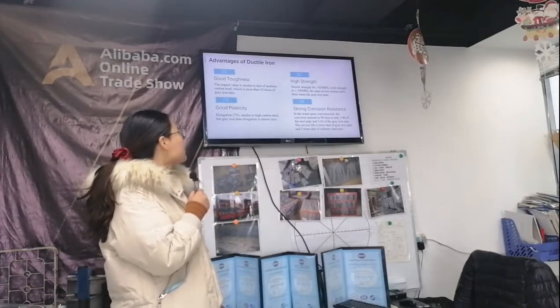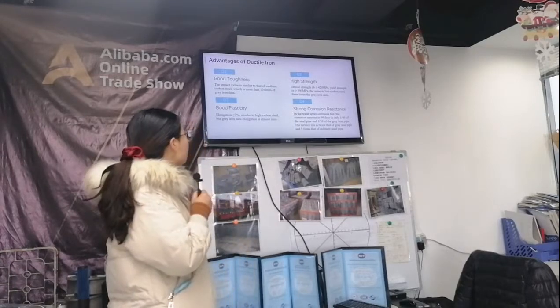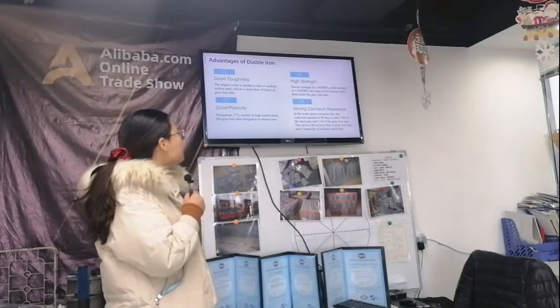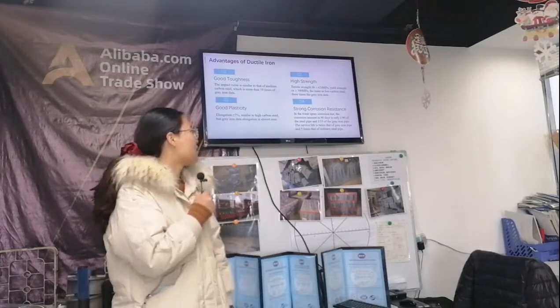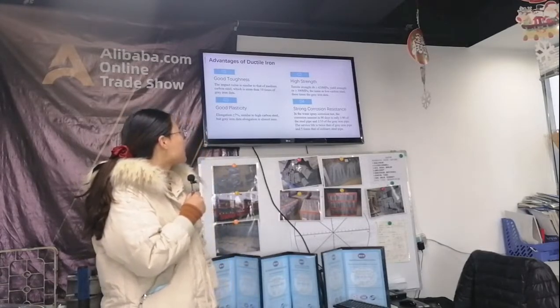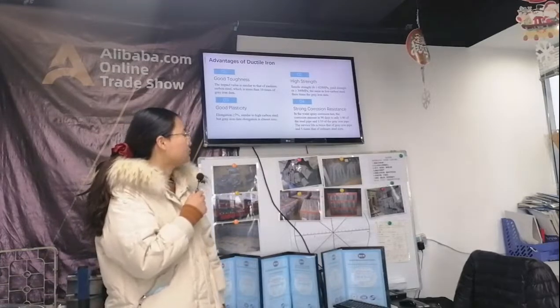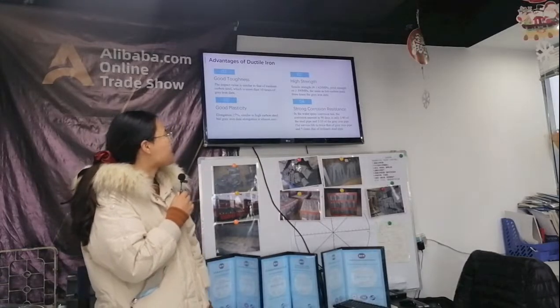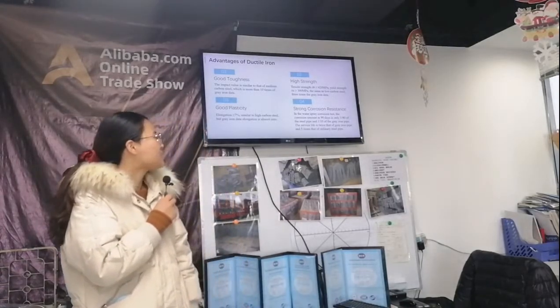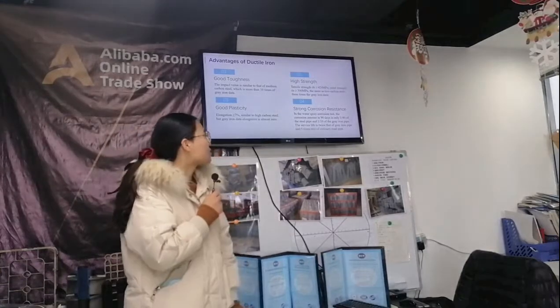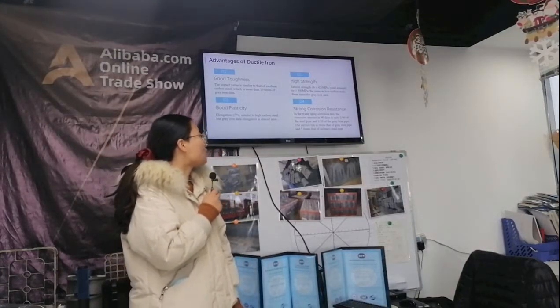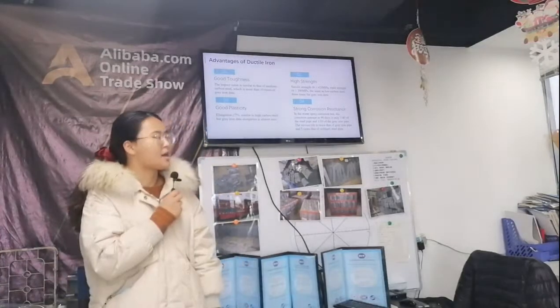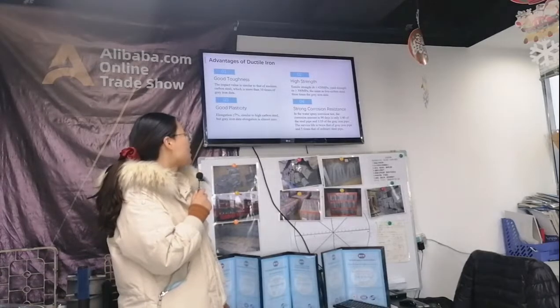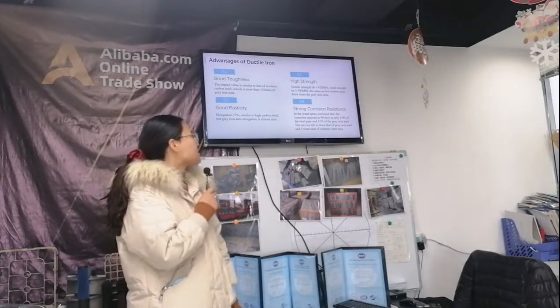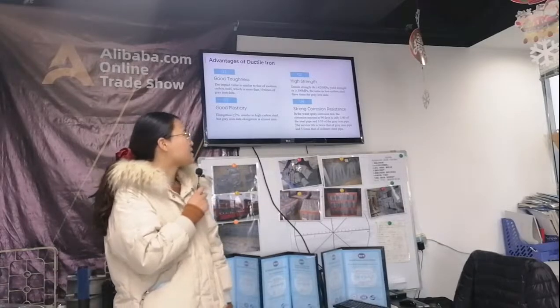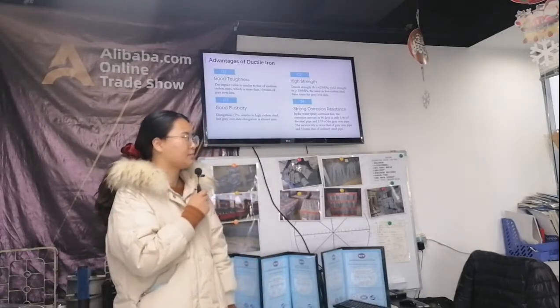It also has good plasticity. The elongation is more than 7%, similar to high carbon steel, but gray iron elongation is almost zero. Next, it also has strong corrosion resistance. In the water spray corrosion test, the corrosion amount in 90 days is only 1/40 of steel pipe and 1/10 of gray iron. The service life is twice that of gray iron pipe and 5 times that of ordinary steel pipe.